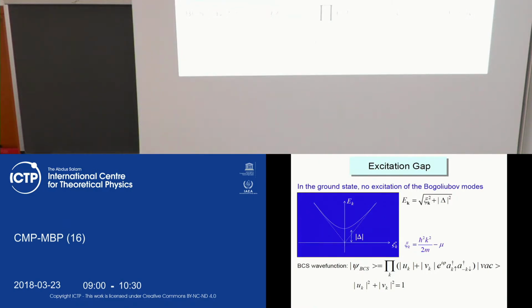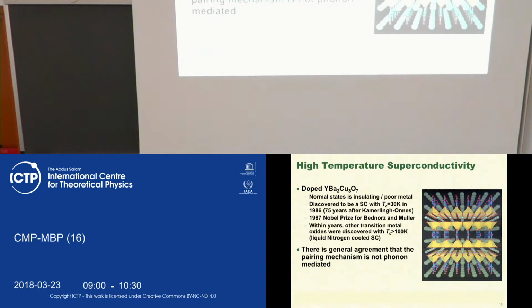This explains several phenomena. First of all, it explains the existence of the gap in the elementary excitation spectrum. It also explains, assuming the temperature dependence given by this equation, that the phase transition is a second-order phase transition, and produces all critical exponents conforming to this statement. This is the variational function of the Bardeen-Cooper-Schrieffer theory, and you see that, instead of varying, one can write it that way, and these are the famous u and v coefficients, Bogoliubov coefficients, which I used in the derivation given in one of the lectures in order to minimize the energy.